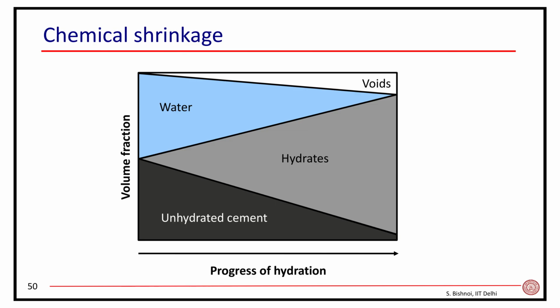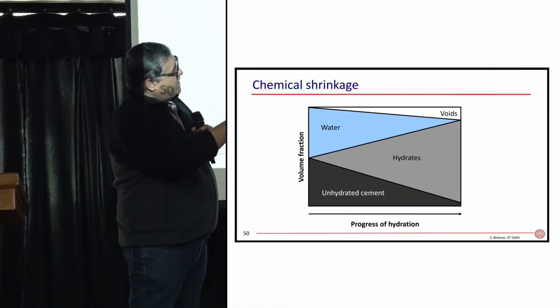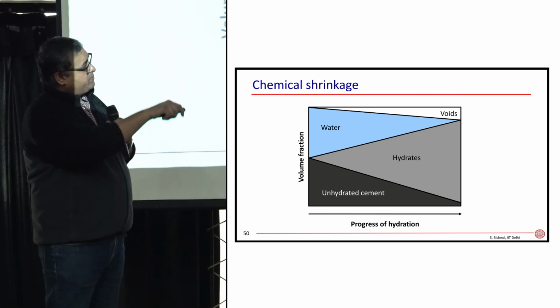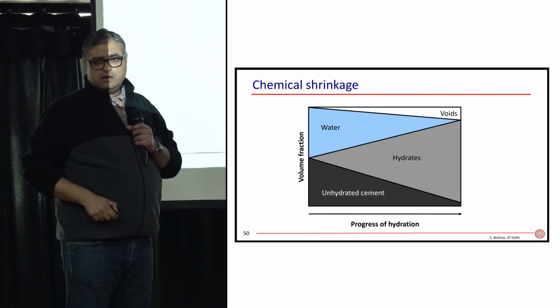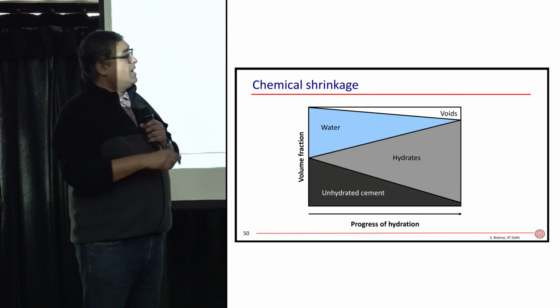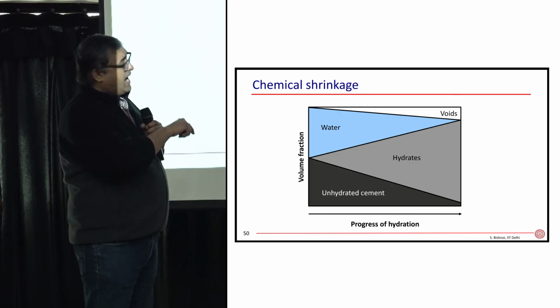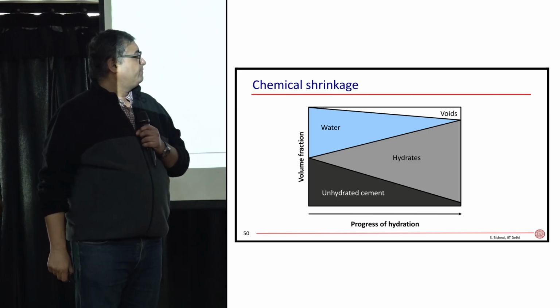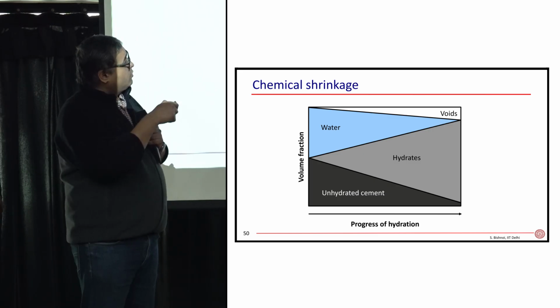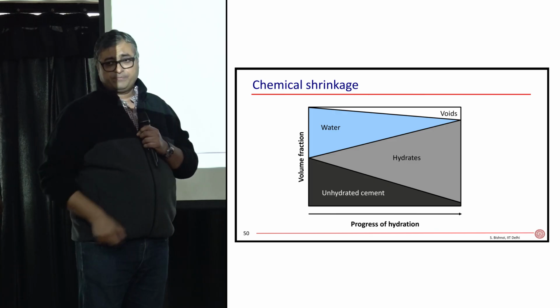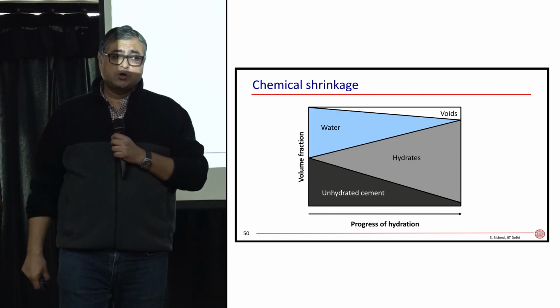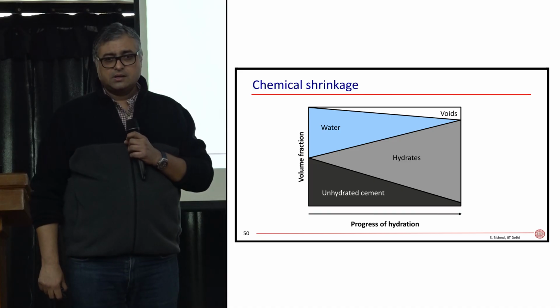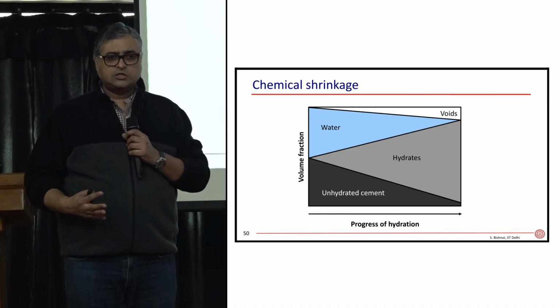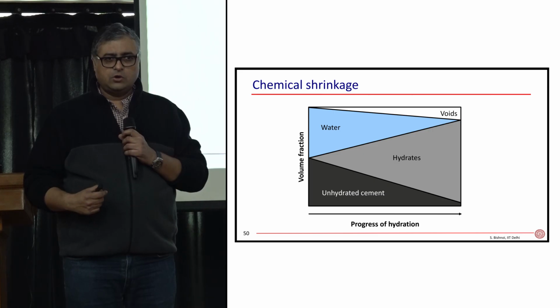One more thing that's happening along with that is, although the solid volume is increasing - so unhydrated cement had this much volume, when it's fully hydrated, that's the volume of the hydration products that are formed - the volume of the solids has increased, but if you take the total volume of water and cement put together, you see that the total volume reduces and you create some voids inside it. This is what is known as chemical shrinkage. Some people also call it Le Chatelier contraction.